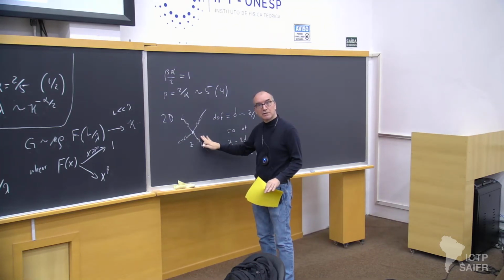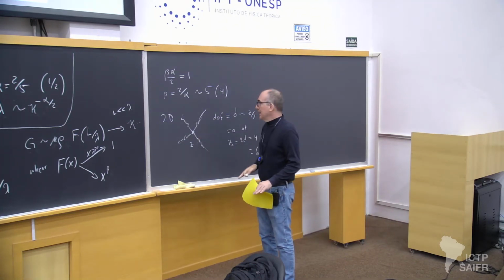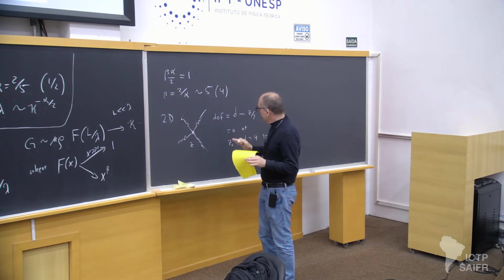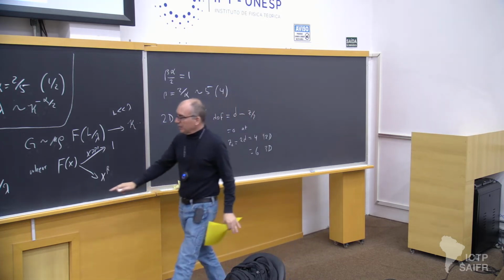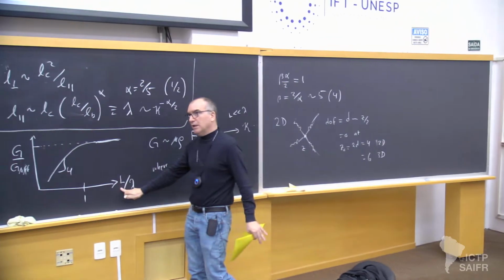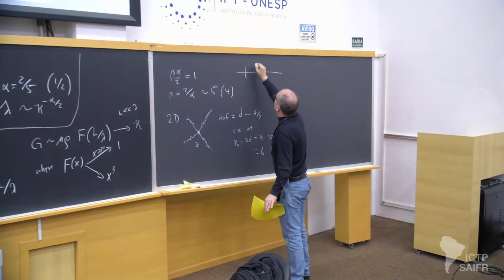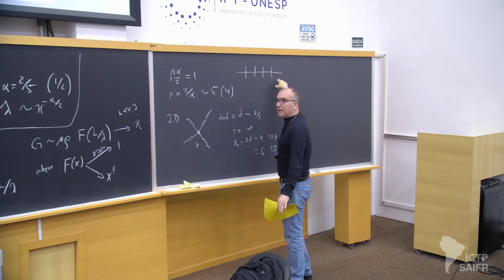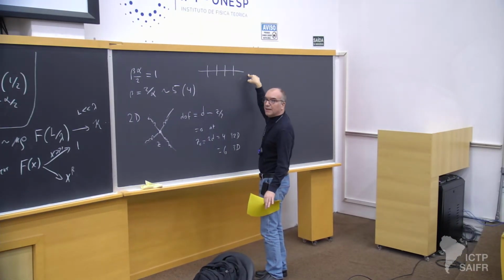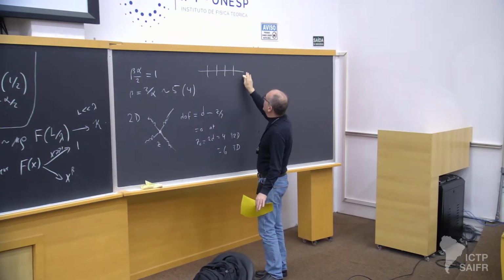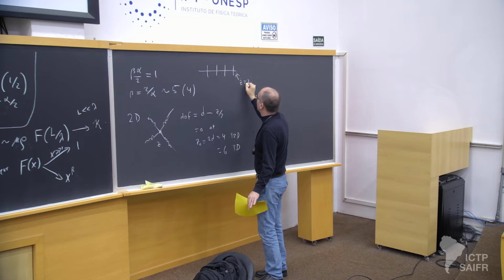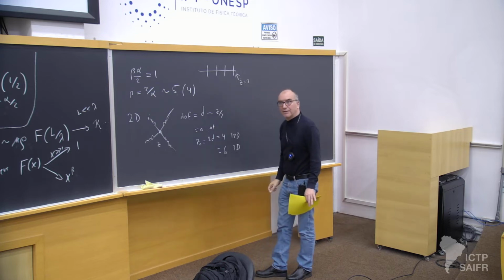Stretching energies. And it's happening at the high molecular weight limit where L goes to infinity. And as L goes to infinity, I have many, many crossing points of a fiber with very few dangling ends. If this is a dangling end with nothing connected here, it's not really relevant. And so this corresponds to a coordination number of 3.